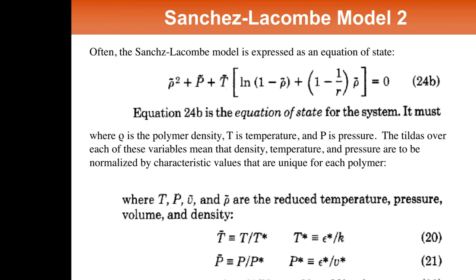And we mentioned that there were extensions to this. The Flory-Rehner model extends it to cross-link systems. The Peppas-Merrill model extends these thermodynamic concepts to cross-link networks where the cross-links are put in place in the presence of a solvent. And all of those models are lattice-based models, and they treat the polymer and the penetrant that are in it as if they're incompressible.